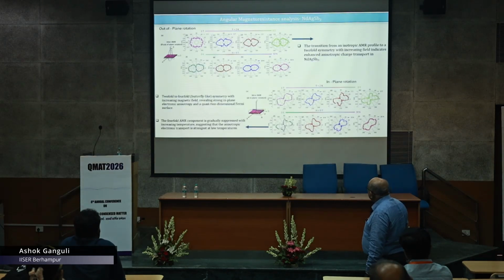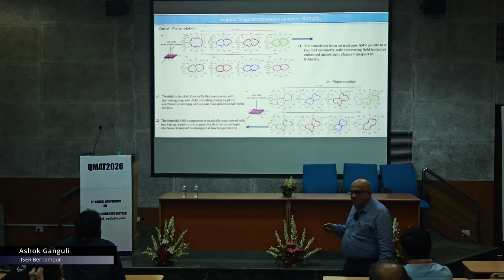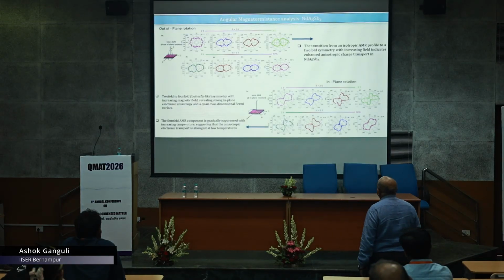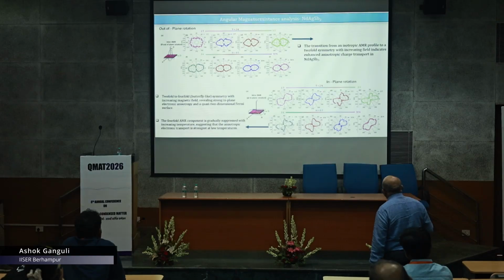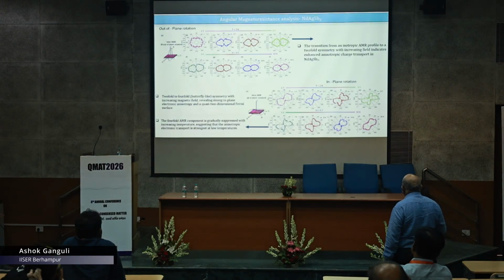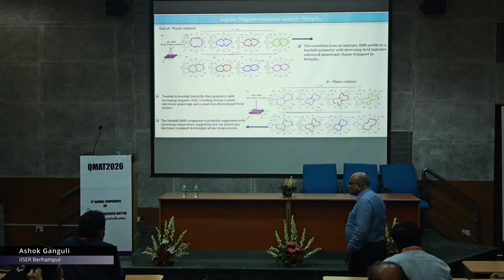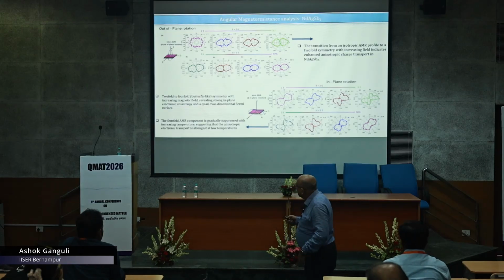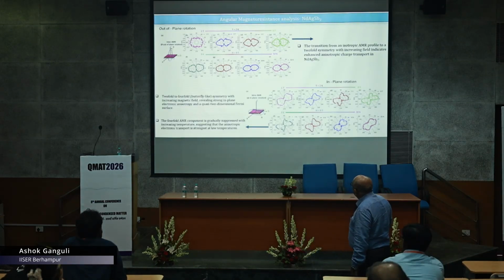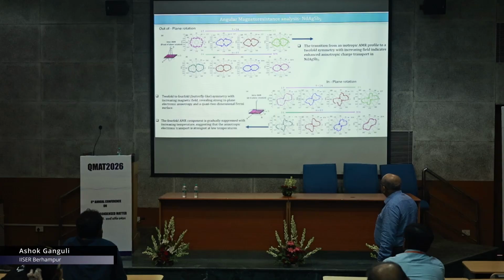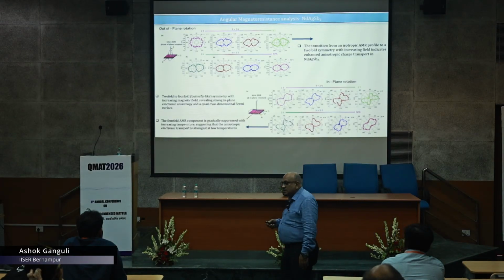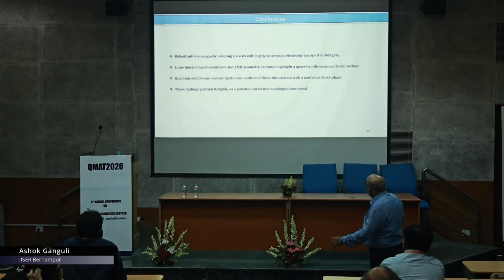We have also done out of plane and in plane measurements, and these were done at Tohoku University. You can see that the in plane rotation, as a function of magnetic field, gives a plot showing highly anisotropic Fermi surfaces, whereas the out of plane rotation does not give this kind of twofold to fourfold change in symmetry. So this is one case.